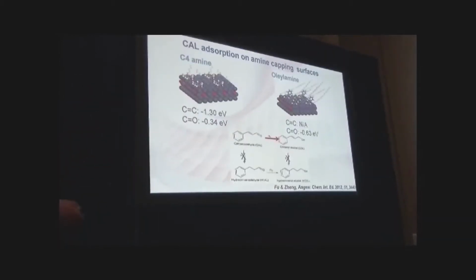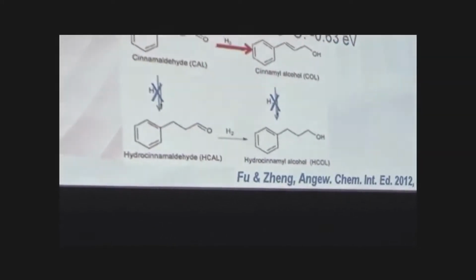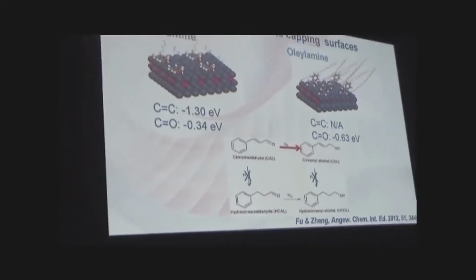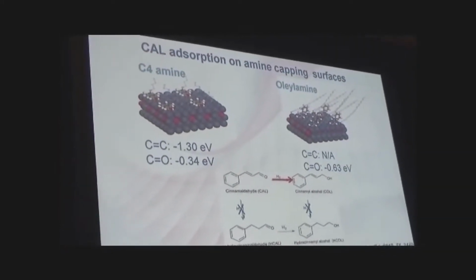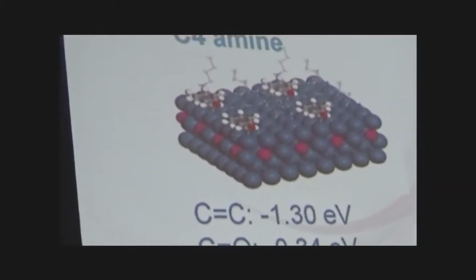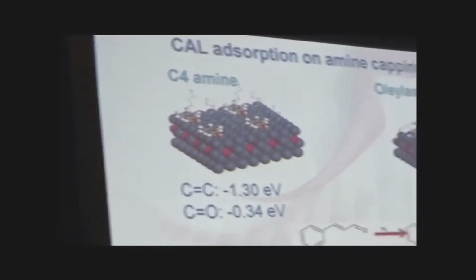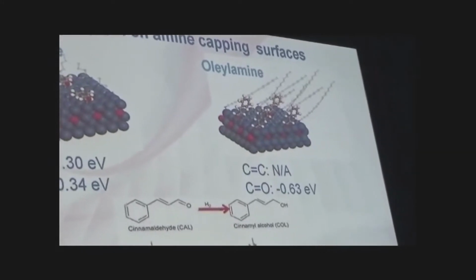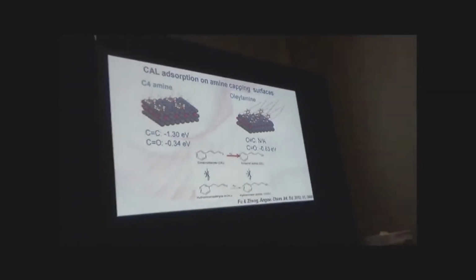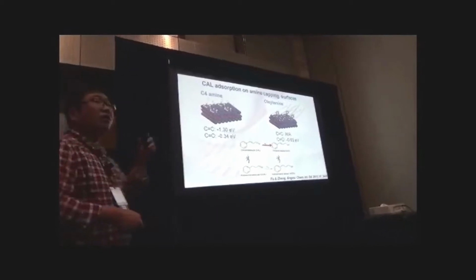And here we can compare the similar aldehyde adsorption on the C4 amine modified surface and the oleylamine modified surface. You can see that in this case, because the C4 amine can be rotated, the surface is still open for the CAL aldehyde. So CAL still adsorbs very strongly.